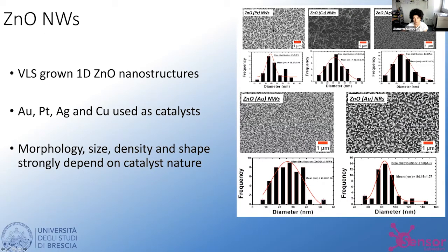Okay, so let's see some examples of the nanostructures that we can produce. Here we see zinc oxide nanostructures using different catalysts. So here, platinum catalyst, copper catalyst, and silver catalyst. And you can see that even if the substrates were at the same temperature, the catalyst influences the morphology. And even with the same catalyst, changing the condensation temperature, you can have different morphologies, so nanowires instead of nanorods. And it's really something that you need to experimentally evaluate during your optimization of the growth process.